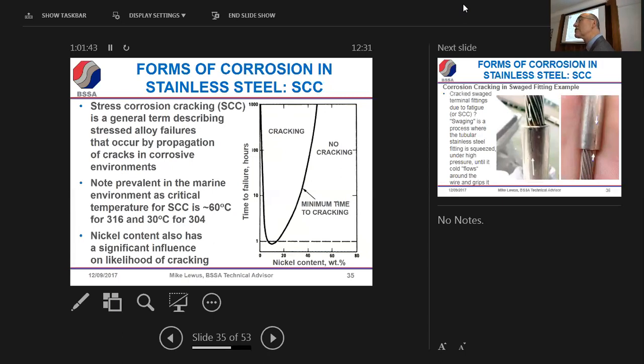Actually, this just shows you the effect of nickel on stress corrosion cracking. Now, I should mention stress corrosion cracking is essentially two prerequisites: a tensile force and some sort of corrosive agent. And the reason it's termed stress corrosion cracking is simply that it wouldn't occur if either of those factors were missing. But in 316, it's not usually found below about 60 degrees. It's not impossible for it to occur below 60 degrees. 304, it would occur at 30 degrees.